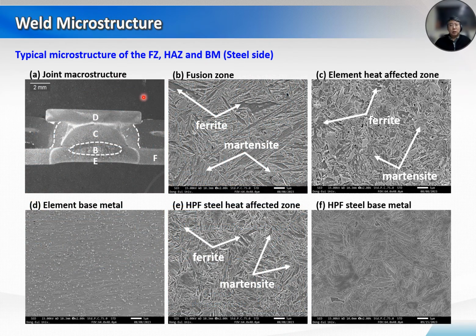We also analyzed the microstructure of each area where the element and the raw steel plates were melted. The molten part of the element and steel shows an overall martensitic microstructure and a very high hardness value of 535 HV due to the high cooling rate of the resistant welding. The hot press forming steel and element heat affected zone show a low hardness value of 273 HV due to some ferrite formation, and the heat affected zone of the element steel shows similar microstructures.